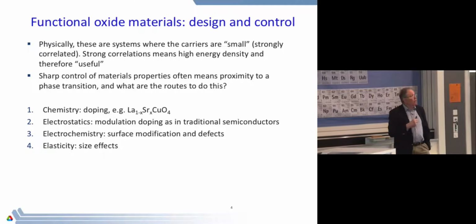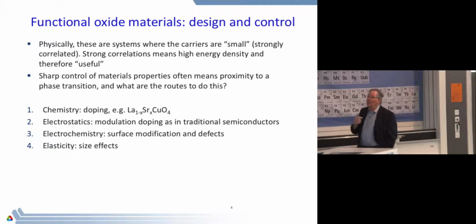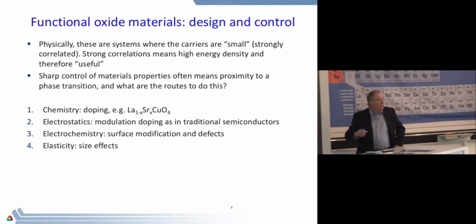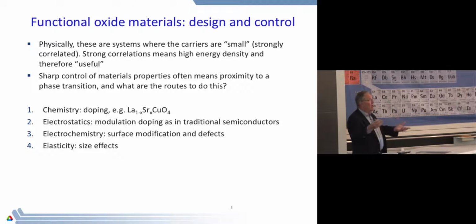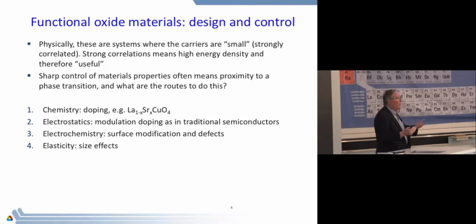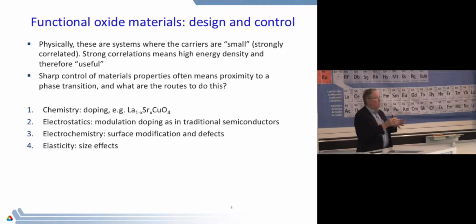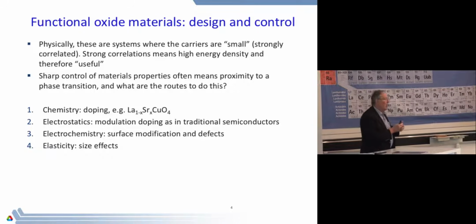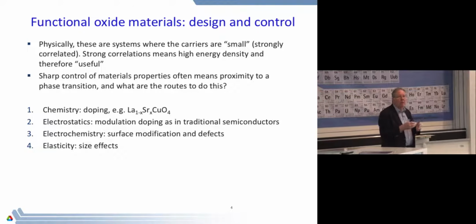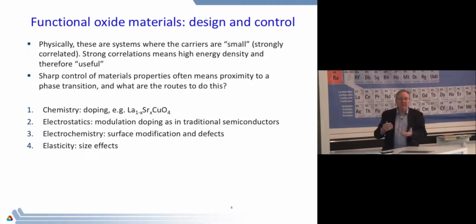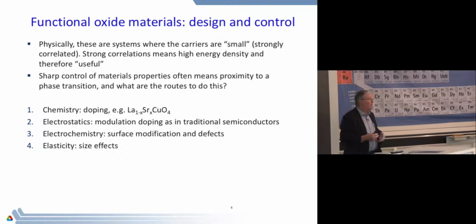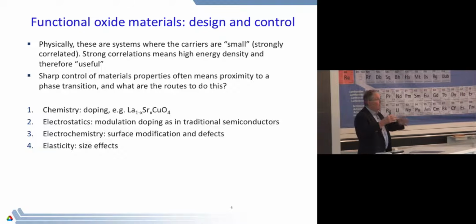One point I do want to make is that most of these materials are in the class of what we would call strongly correlated. What does strongly correlated mean in this context? Strongly correlated is that the electrons which are flowing around, typically in those transition metal oxide layers, are small. I mean, what's the sense of an electron being small? Well, how big is an electron in silicon? An electron in silicon is actually about 10 nanometers across.